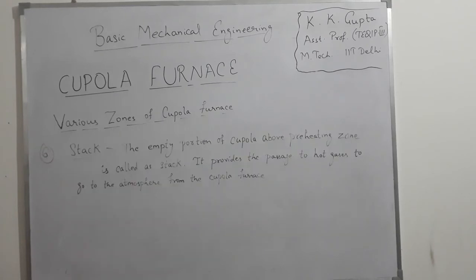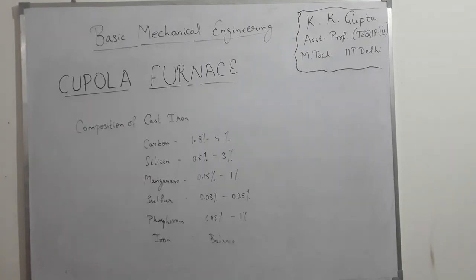Sixth zone is stack. The empty portion of cupola above preheating zone is called as stack. It provides the passage for hot gases to go to the atmosphere from the cupola furnace. You can note down the composition of cast iron. Carbon is 1.8% to 4%, silicon is 0.5% to 3%, manganese is 0.15% to 1%, sulfur is 0.03% to 0.25%, phosphorus is 0.05% to 1%, and the balance is iron.